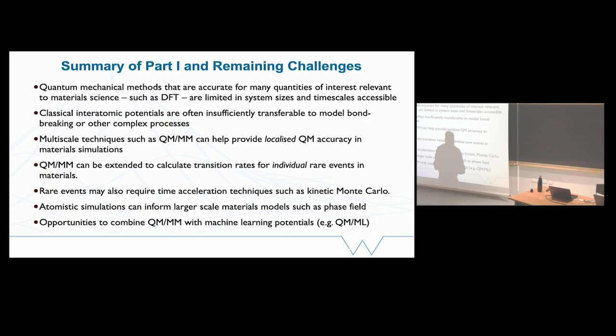Separately from that, we also have some smearing, which means that we're treating the electrons as not being at 0 temperature. That's somewhat artificial. It's to make the convergence of the DFT easier, and typically the amount of smearing that you use is rather higher than the true temperature. So often you would use maybe 300 Kelvin for your simulation if you want to do room temperature, but your smearing would correspond maybe to more like 1,000 Kelvin, so that you don't need quite such a dense sampling of the Brillouin zone with your K-points. So that's maybe more detail than you wanted. Thank you so much. Yes?